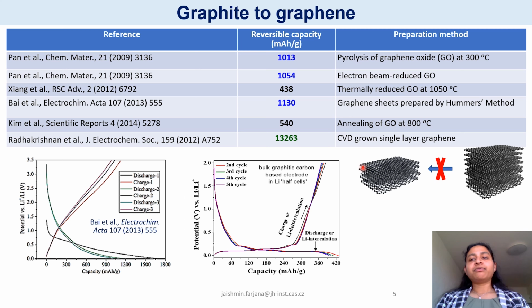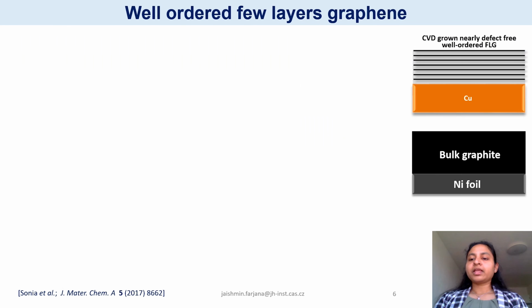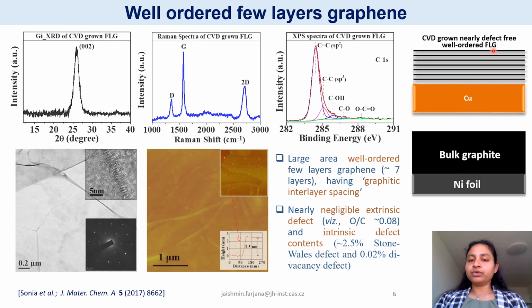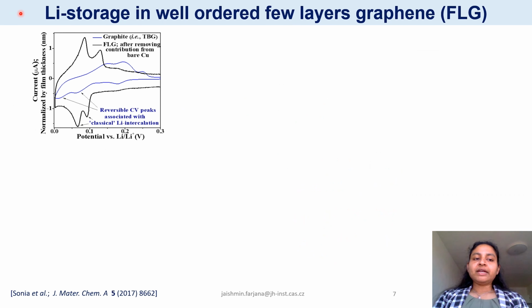So in our work we wanted to get rid of those extra factors, and we just wanted to see if we reduce the dimensional scale from graphite to graphene, how it advantages or disadvantages the lithium intercalation. For that, we deposited bulk graphite on nickel foil using chemical vapor deposition method, and in the same method we also prepared a defect-free, well-ordered few-layer graphene, approximately 7 layers of it.